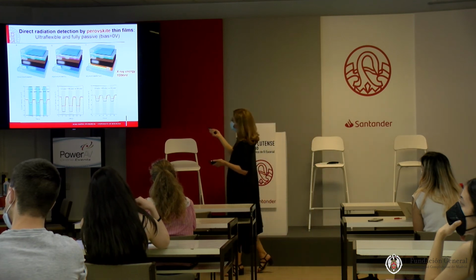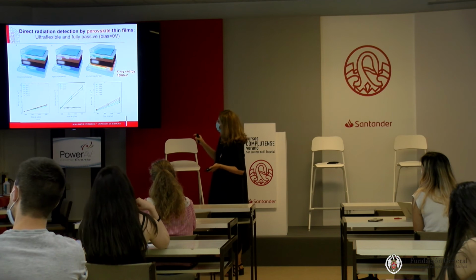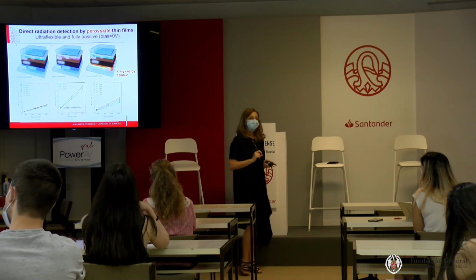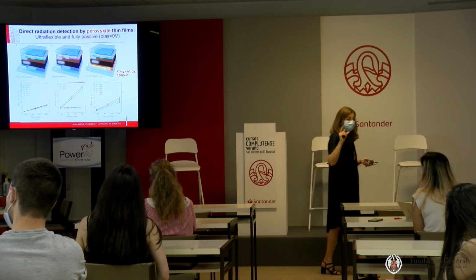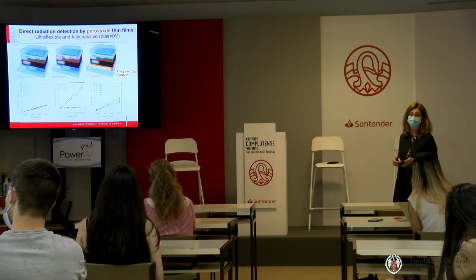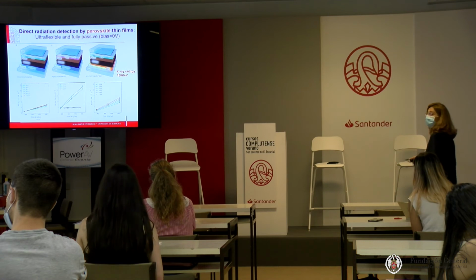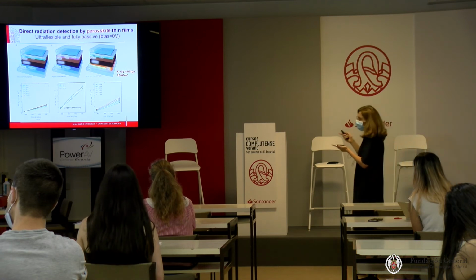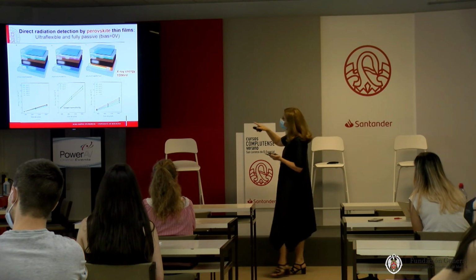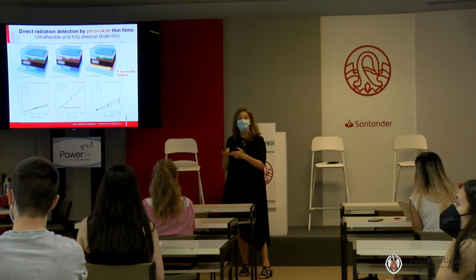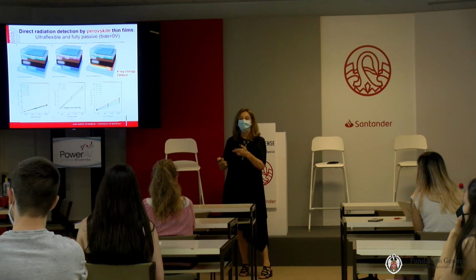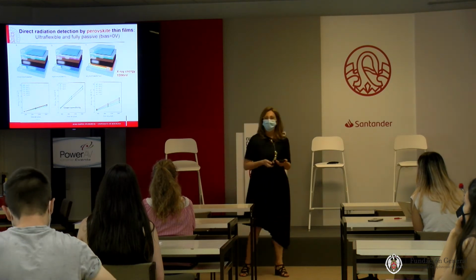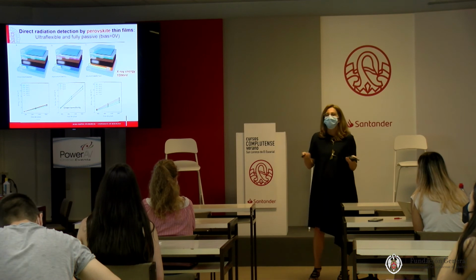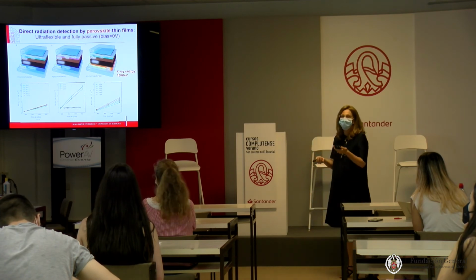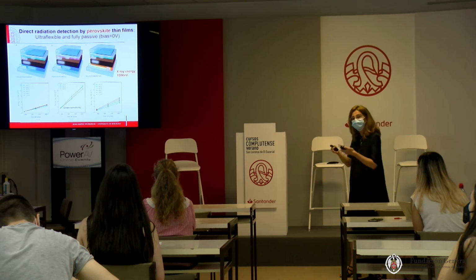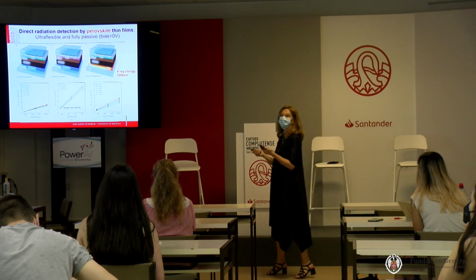What is the difference? You see already the intensity, but if we plot the delta I over the dose rate, you see that one of them has a definitely higher slope, the central one. So this one has a much higher sensitivity than the others. Unfortunately, as I showed you in the previous graph, this does not bring also the best dark current and the best limit of detection. So often you will have a trade-off between these parameters, or somebody will have to find another material or another combination that is able to get all three parameters at best together.